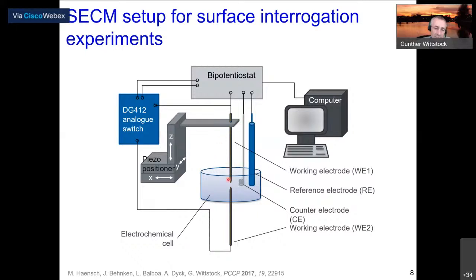So we use a setup which is very similar to what I showed you before, but now we have two microelectrodes. One microelectrode contains our sample. I will explain that in more detail later. And the other one is a microelectrode which we use as a probe, or as it's called here, for interrogation. So that is our tool, and that contains our sample, but they have approximately the same size. And then again, we have a reference electrode and an auxiliary electrode, positioning system, bipotentiostat, and we also use an analog switch, which can be programmed. That analog switch can change the function or can interrupt the connection between the potentiostat and two electrodes. So we can apply a potential, but we can also keep them at open circuit potential so that no charge can flow over the external circuit. You will see in a moment why this is important.